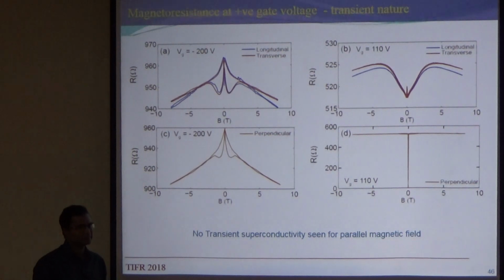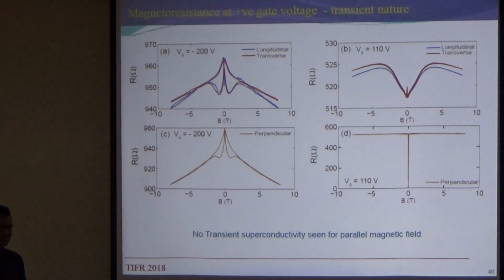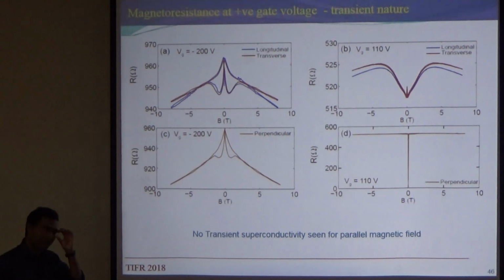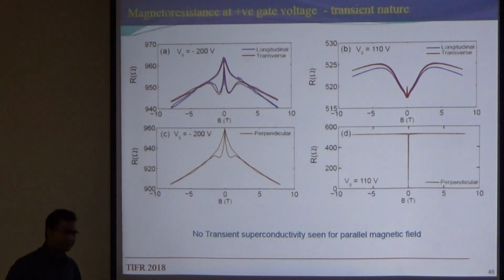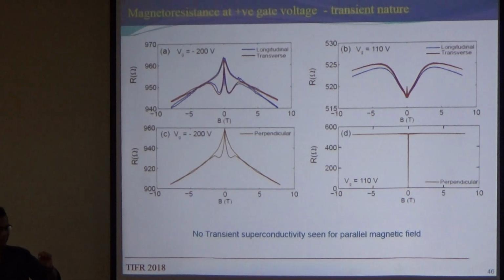So, the reason I am asking is that you see this strange time dependence. Mm-hmm. Now, when you sweep very fast, you might have trapped flux in your superconducting magnet that will slowly relax. That's right. Yes. Might be. So, that relaxation might be because there is a small magnetic field which is slowly relaxing.